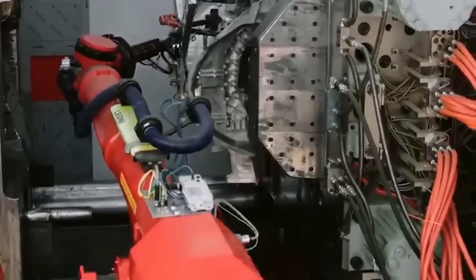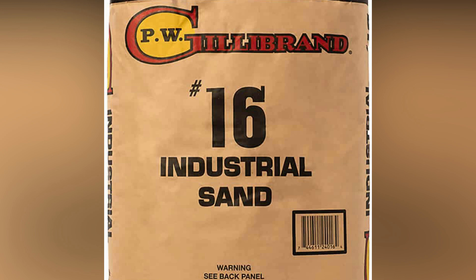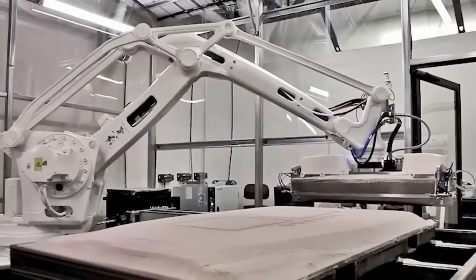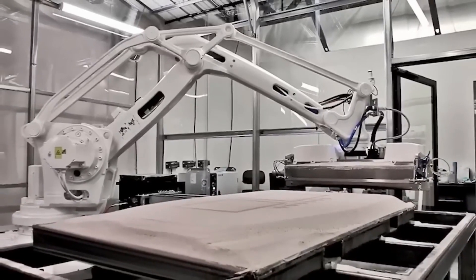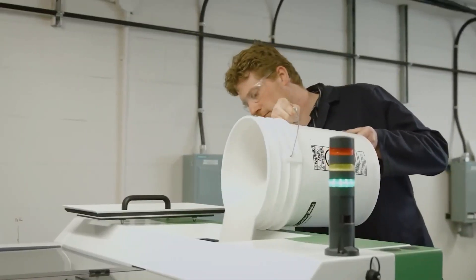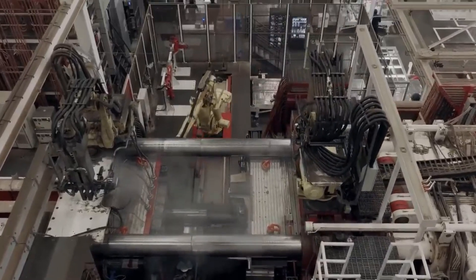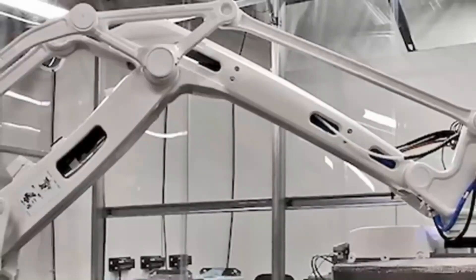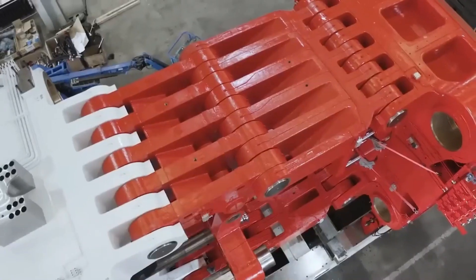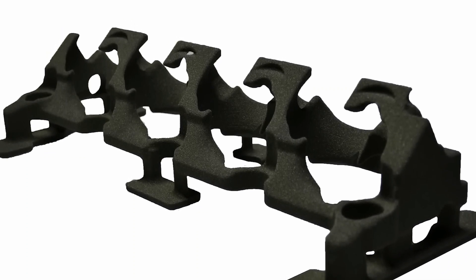Recent advancements from European casting experts, as well as discoveries in Japan and the United States, involve the use of industrial sand to successfully 3D print complex and detailed molds. A sand with a high silica concentration — typically used in glass manufacturing and construction — is used to create molds. Layers of sand are laid down by a giant printer's arm, and binding agents are added for rigidity. This material is easily recyclable, capable of producing detailed features in complex designs, allowing speedy creation, disposal, and repurposing of new molds at as little as 3% of the cost of conventional mold production and in less than half the time. Hollow spaces can be created by incorporating 3D-printed sand cores that can be removed easily later.